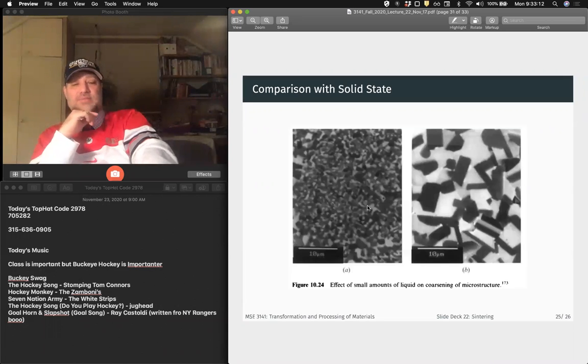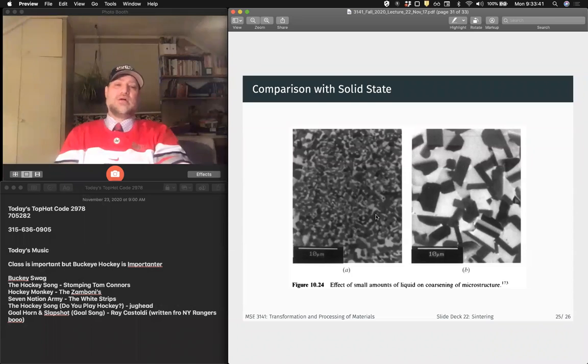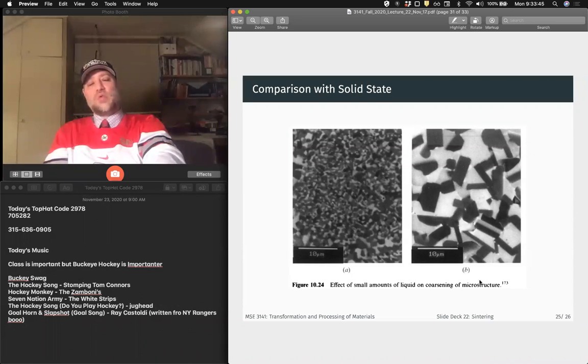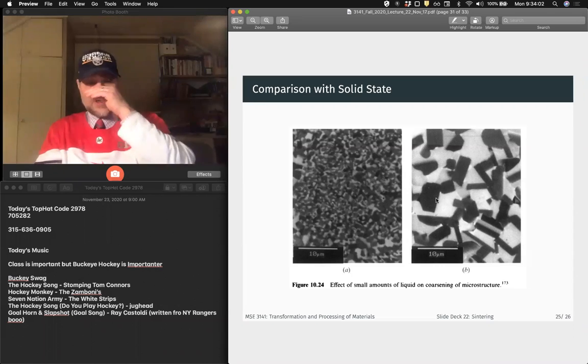I forget what the material system is, but anyway, you can see the effect of this sintered at the same amount of time. You can see we have multiple phase particles. So we have powders that were made of multiple phases mixed together, and then sintered. You can see the difference that a thin grain boundary film of liquid makes. These were sintered under the same conditions, same time at temperature. This one on the right here is just slightly doped. So you had a little bit of eutectic melting in this one on the right, where we don't have that on the left, right? So you can see you not only have greater densification, but you also have much larger grain growth.